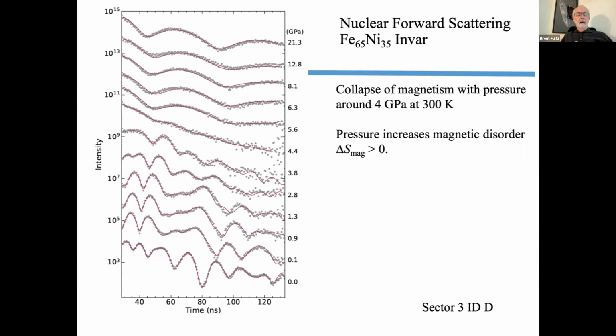This is the pressure dependence of the nuclear forward scattering at 300 Kelvin. The fits using CONUSS are these red lines here. And with your eye, you can see pretty well that it's magnetic down here, and up around 4 gigapascals, it goes non-magnetic, and we get a thickness beat here. But basically, you can see the range where we have the magnetic behavior below about 4 gigapascals, and then we can look at the magnetization, the hyperfine magnetic fields versus pressure here, and use that for our magnetization.